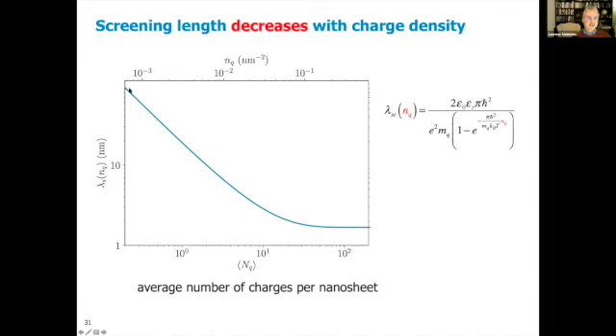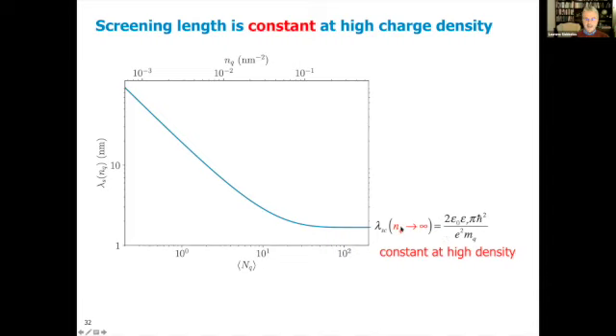And then, interestingly, you start with, of course, when NQ goes to zero, a very long screening length, so there is no screening, and then the screening length becomes shorter when the density of charges or the number of charges per nanosheet increases, and then interestingly at very high density it becomes constant, and that's different from 3D where the screening length really goes through zero. And this constant screening length at high density is due to the fact that even if you have a high density in a very thin two-dimensional material, there are always field lines going through the surrounding medium, which in this case is the hexane solvent with a low dielectric constant of only 2. So you never reduce to a zero screening length because you always have interaction via the solvent.